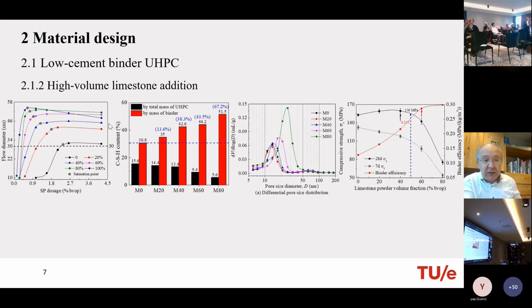Well, we also look at CSH formation, how much CSH we have, by mass of binder and also by mass of UHPFRC. And also here we can see the effect of more limestone powder and less cement. Here is an interesting one. I cannot go into details in all these slides, but here we can see that at 50% limestone powder, it seems like a maximum amount or an optimum dosage, that there the strength is highest. So we can go up to 50% limestone powder in this mix and have the same strength.